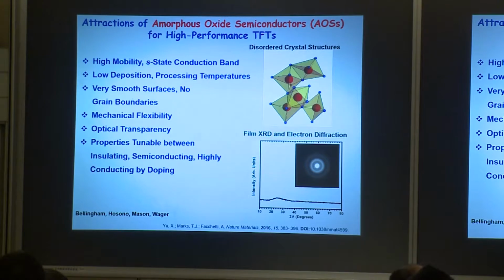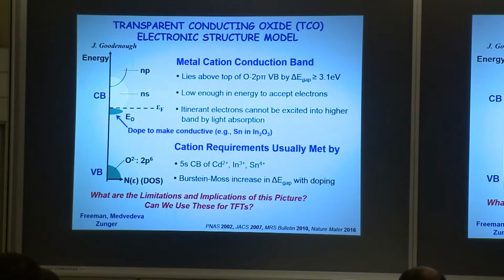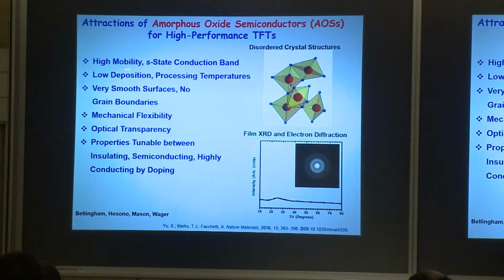So you might say, probably in the 1950s, people said, why would you need to grow them at low temperature? Nobody ever thought, well, if you grow at low temperature, you can grow them on plastic. But you still, because of this S-state band, you still get good mobilities. You get as good mobilities from the amorphous material as from the crystalline material. That is extraordinary. And sometimes better, because you don't have grain boundaries in the amorphous material.